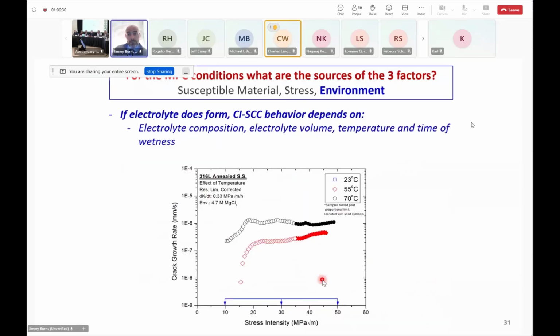Now, again, we're talking about necessary but not sufficient, right? Let's say an electrolyte does form, okay? Just because an electrolyte does form does not mean that CISCC is going to happen, right? So you could have a susceptible material, okay? You could have a stress, and you could have this environment, but that doesn't necessarily mean that you are going to have CISCC. It can happen. Those are the things necessary for it to happen, but it doesn't necessarily mean it's going to happen. And so the extent of CISCC susceptibility is going to be dependent on what is the electrolyte composition, what is the electrolyte volume, what's the temperature, what's the time of wetness? How often is it wet?